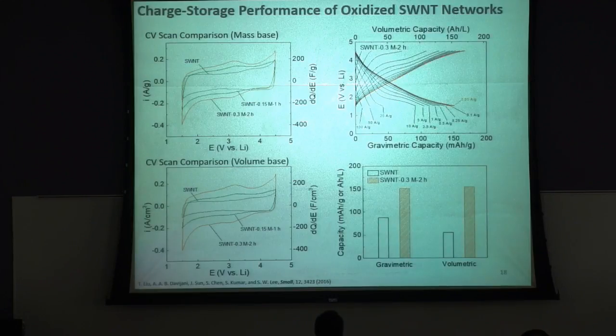So this CV is compared based on the unit mass of the electrode, right? Then if we compare this CV with the current normalized by the unit volume of the electrode, you can see a further increase of this current because of the densification process during the hydrothermal oxidation process, right? So then this is the gravimetric capacity and volumetric capacity. Now the capacity has been increased to 150 milliampere hours per gram.